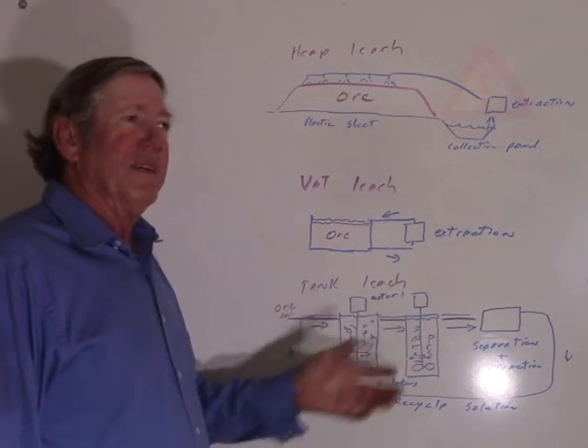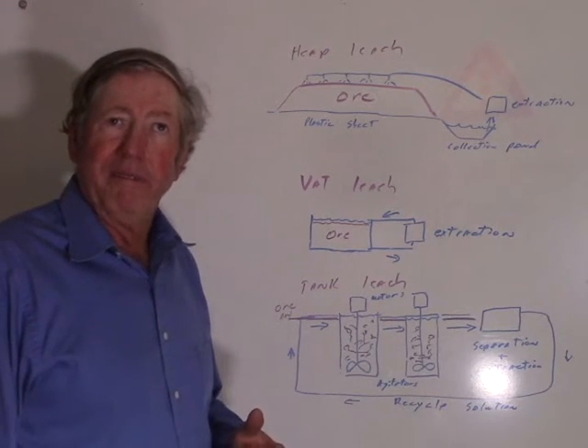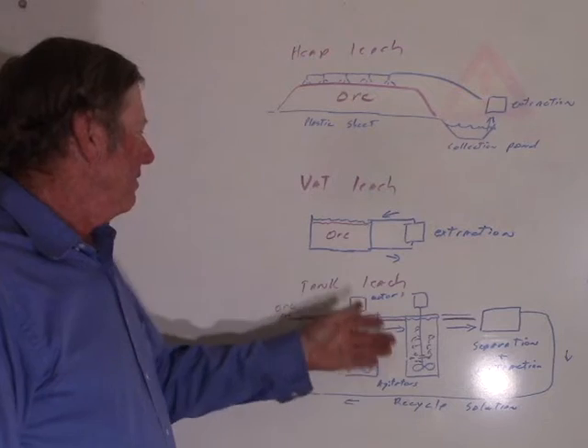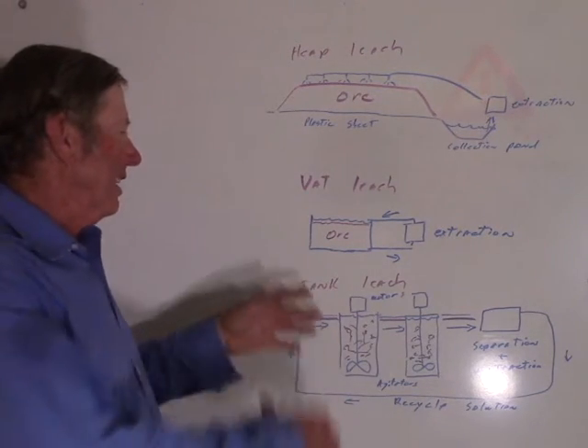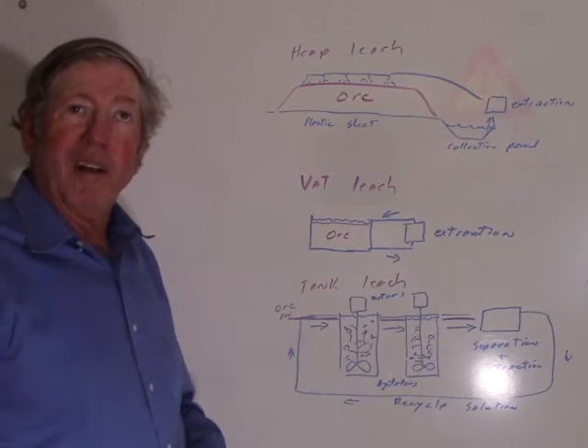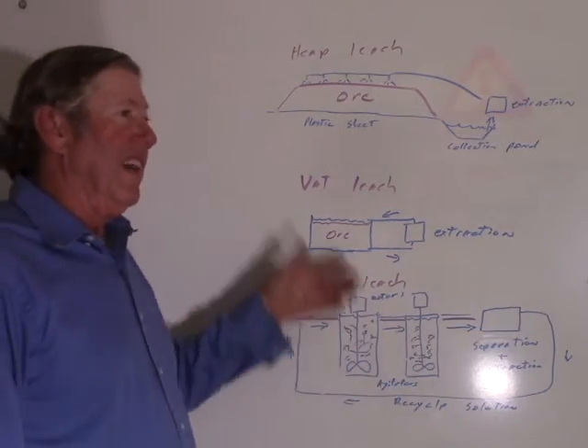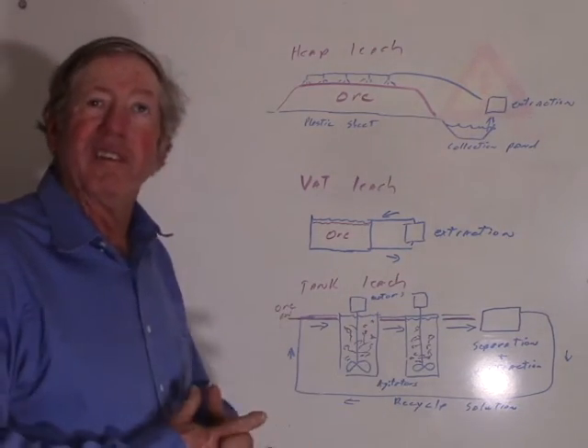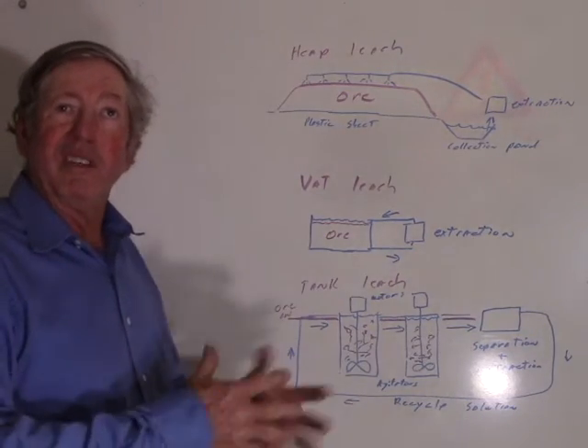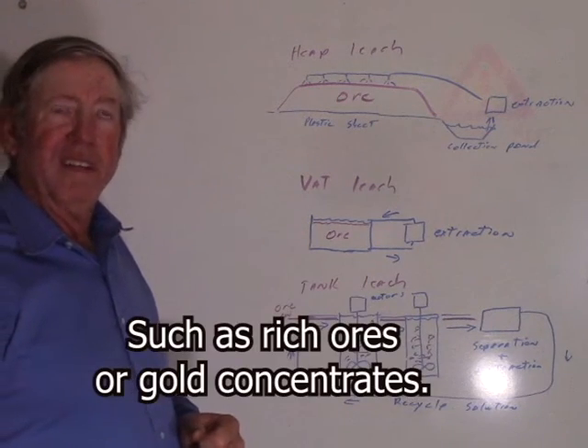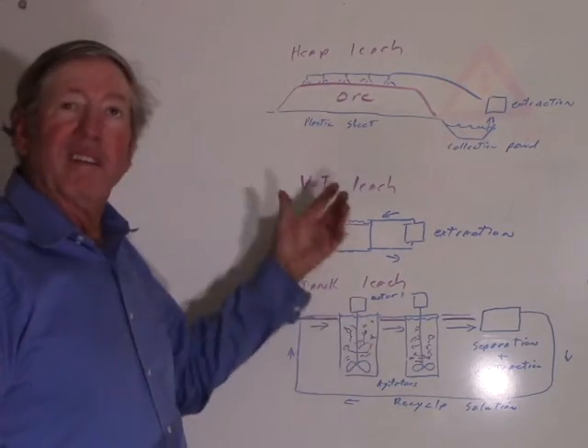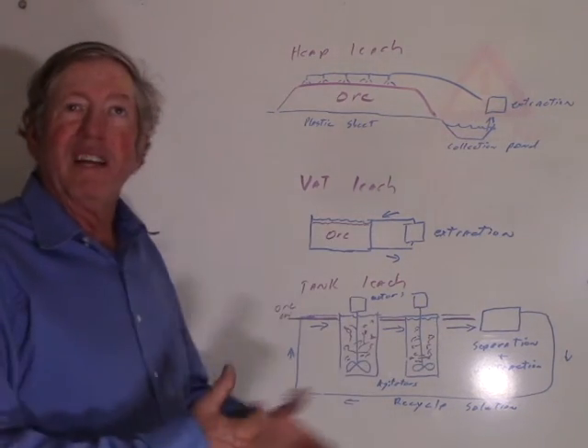This is your most effective method, typically designed to give somewhere in the neighborhood of 90% recovery. It also has the highest capital cost per throughput — you've got to have tanks and there's a retention time. If you're doing a thousand tons a day and it takes two days to process the ore, you need to have 2,000 tons of rock in slurry form — typically around 10,000 tons of slurry in tanks being stirred at all times, using up energy. This would be used for higher grade materials. The finer you grind it and the more you agitate it, the faster things are going to go.